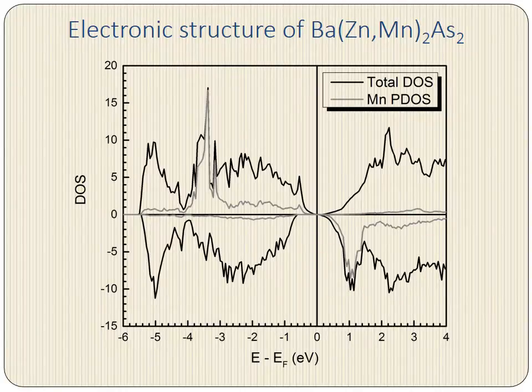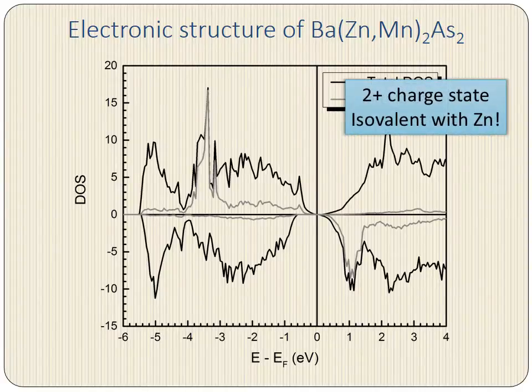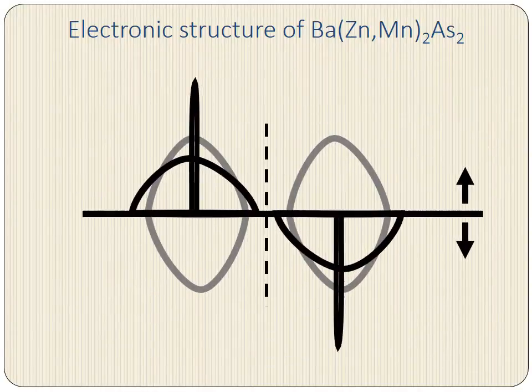Therefore, we can conclude that the manganese atom is in the 2+ charge state and is therefore isovalent with the zinc atoms. This is important because it means when we swap out our zinc atoms for manganese, we are not introducing any spurious charge carriers into the system. Next, I want to discuss the hybridization of the manganese moments with the occupied arsenic states and the unoccupied barium states. For this, it is easier to refer to the following schematic.